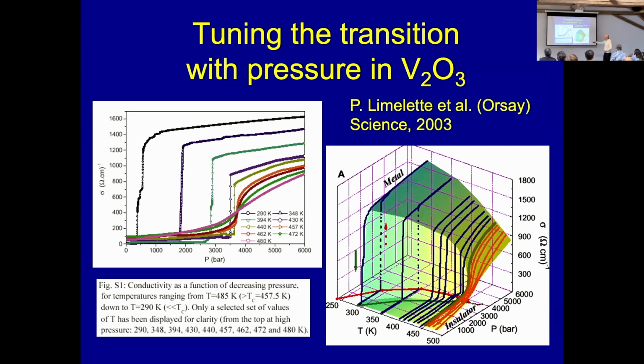You see that above the critical endpoint, which is at very high temperature in this material because it's an oxide, the critical endpoint is at 450 Kelvin, you see this sort of smooth increase. But now as you go close to Tc, this thing becomes S-shaped, very characteristic of the order parameter of an Ising model. There is a jump as you go below Tc. You can even evidence the hysteresis.